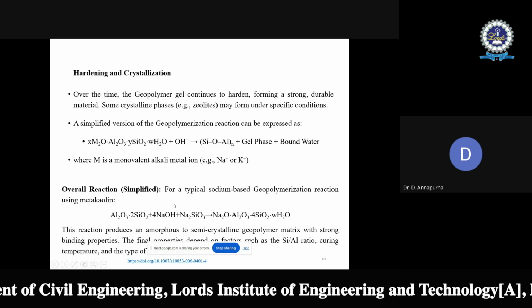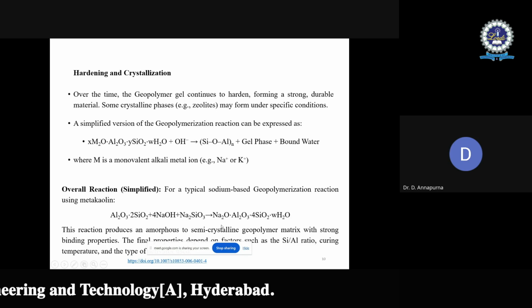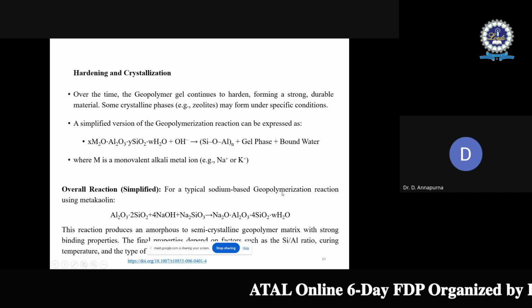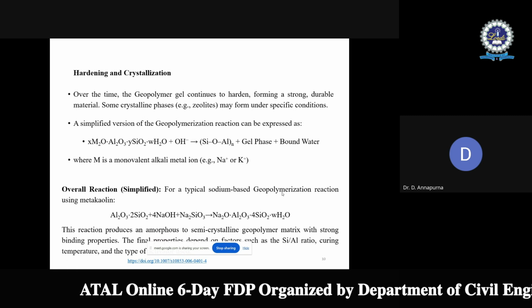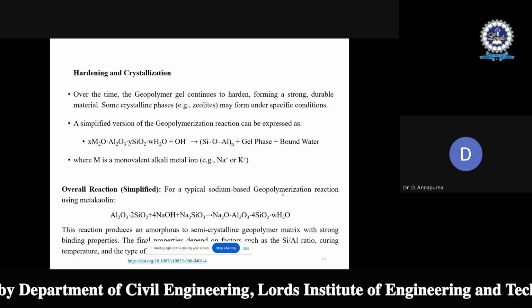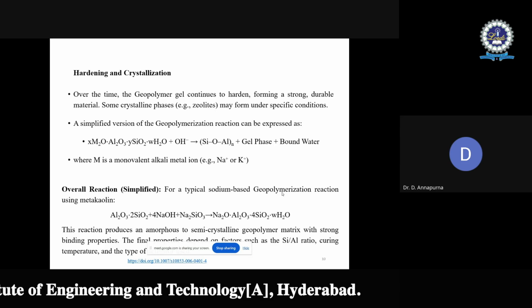So here, alkaline liquid is prepared using sodium hydroxide and sodium silicate. When this reaction occurs, it is going to give a geopolymer product of the form N-A-S-H. So N-A-S-H gel is the final geopolymer product which is going to be produced when the source material is rich in silica and alumina. So that is the reason it is also called N-A-S-H gel.